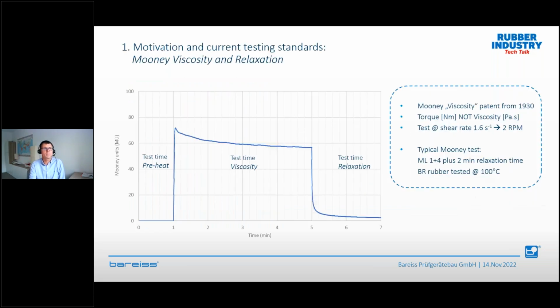So what is a standard test? What we all know since many years in rubber industry, it is a Mooney test. It's a very important test. It's a well-known test, but honestly, it's a patent from 1930, so some years old. And when we are honest, we are not measuring a viscosity which has a unit in Pascal seconds. It's just a torque. What we measure is a torque as a function of time. And that is what you see on the graph on the left side.